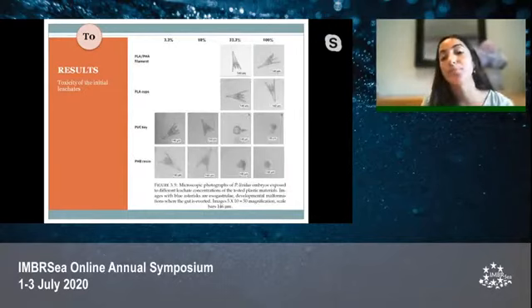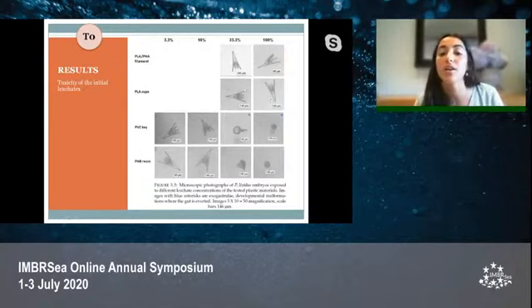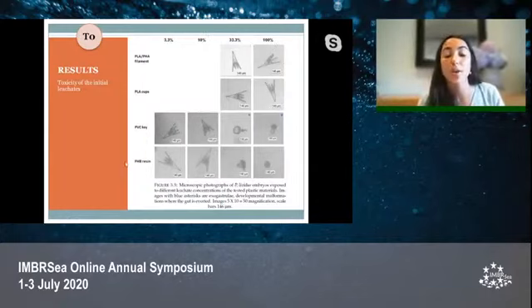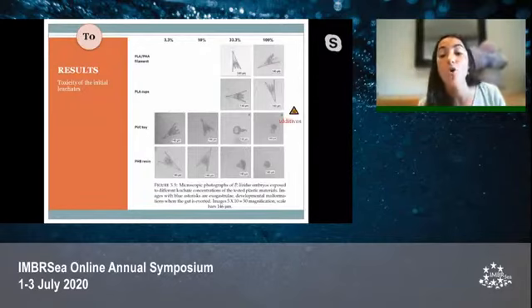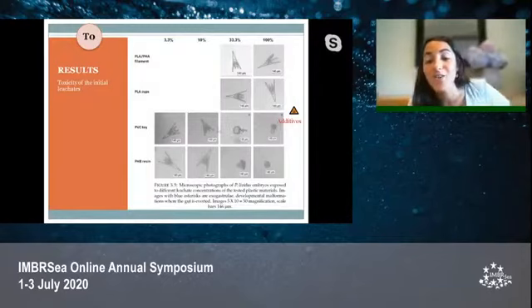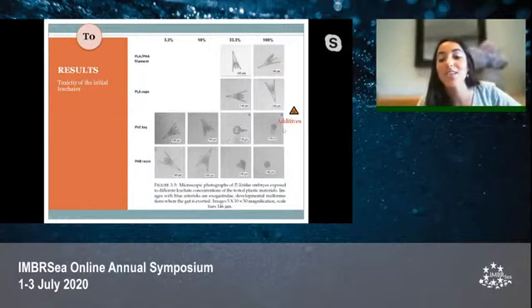In this slide, you have some microscopic photographs of the larvae of the initial leachates, and again, for the first two materials, you can clearly see that the larvae grew perfectly well here, even for the most concentrated treatment, while for PVC toy and PHB resin, for concentrations above 33.3, you can see developmental block. And going a bit deeper, in PVC toy, it seems that the additives and mainly the plasticizers that it contains trigger this developmental block.